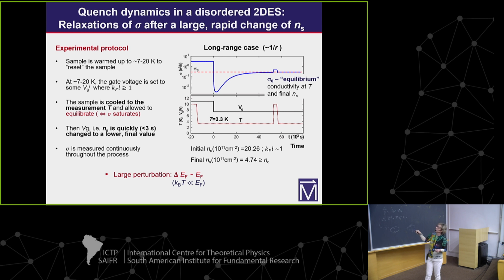At that point, when it seems that it doesn't change anymore, we warm up to some high temperature, cool back down again, and we get the same value. So it seems that we waited long enough here. You see that this conductivity initially overshoots this final, what appears to be equilibrium value, in this case by orders of magnitude. We still don't know why.